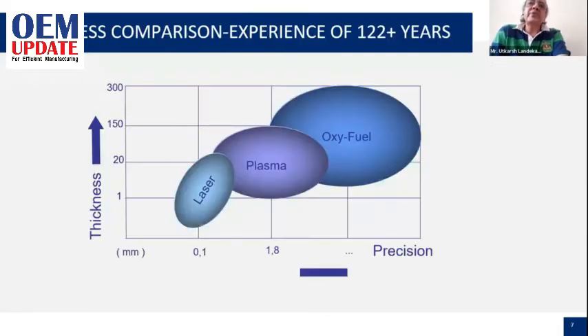Our 122 years of experience gives us a clear-cut bubble diagram which shows the operating range of all three processes. Let's say laser will be 0.5 millimeter up to 25 millimeter, plasma 1 millimeter up to 150 millimeter, and oxyfuel 6 mm thickness up to 300 mm. This is for mild steel. Of course, for stainless steel and aluminum, the things are a bit different.